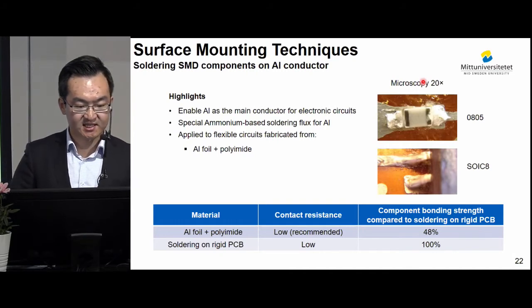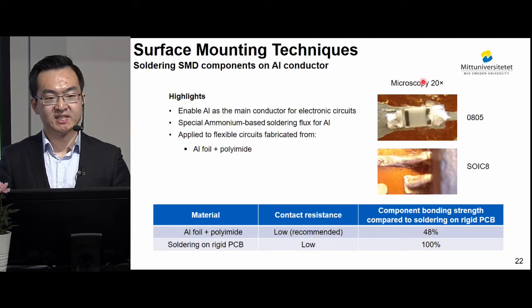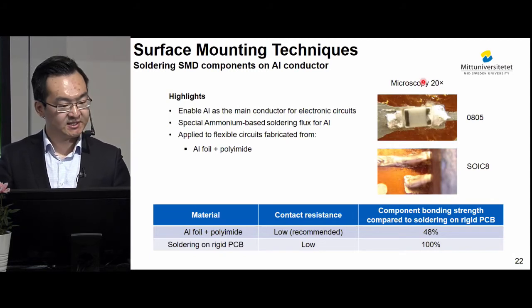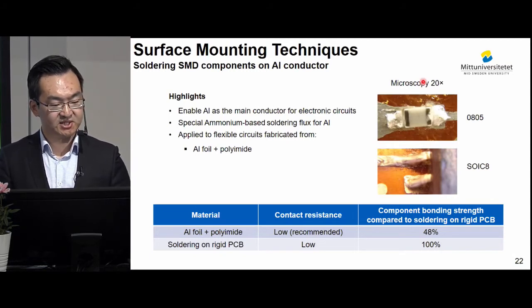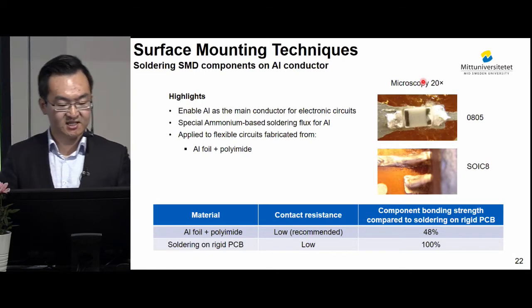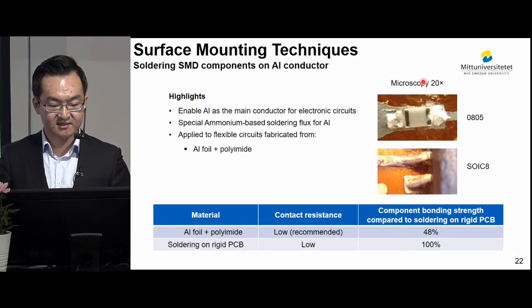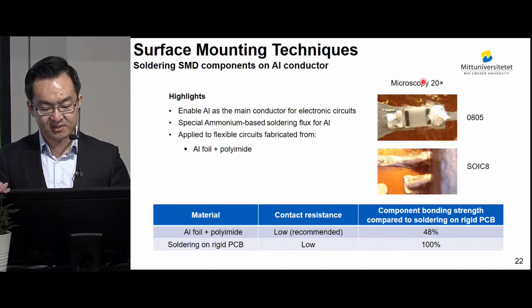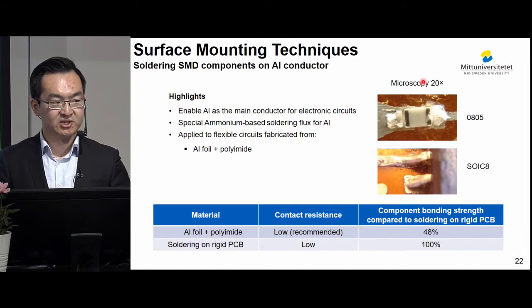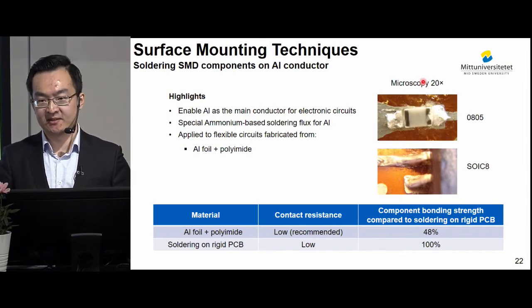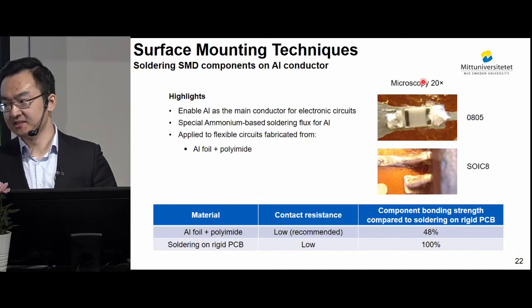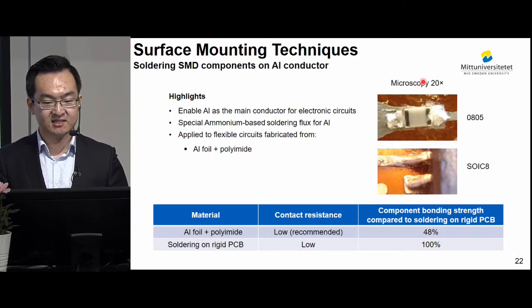And because this technique requires a soldering temperature of 280 degrees, it is only applied to flexible circuits made from aluminum and polyimide. The result showed that the contact resistance measured from the components mounted is low, and the component bonding strength was almost half that of components soldered on rigid PCB. And that's why we also recommend this method to be used in implementing electronic systems.